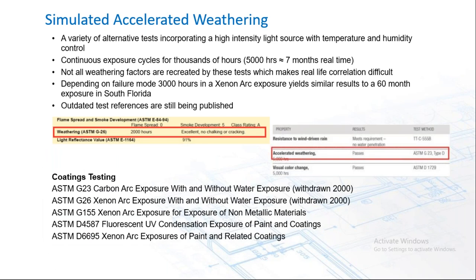Simulated accelerated weathering. Well, this is the automotive crash test of the coatings industry. We simulate accelerated weathering by applying our coatings to these test samples and exposing them to rigorous weathering cycles in laboratory conditions. They incorporate a high intensity light source, temperature, humidity, and we expose these for continuous cycles of up to thousands of hours, 5,000 hours, and actually 7 months in real time.